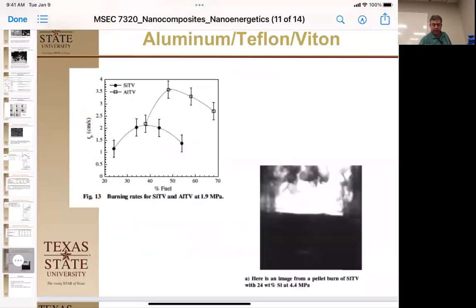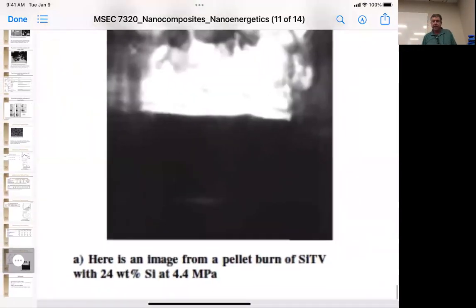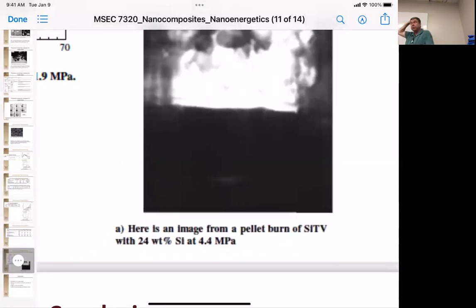Okay. And so what that kind of looks like as they burn, they actually put these pellets on it. They put a high-speed camera on it, and the dark is what they're actually measuring. You're going to measure from where it starts, and then they're measuring how far it goes down over time. And then that right there is all the volatiles that are coming off when they do this. So this is an optical burn. And notice this particular one is the 24%, which is the fastest one for silicon. And they have it at 4.4 megapascals. Again, they're doing it at an increased pressure to emulate being inside a rocket tube, and that buildup in pressure inside a rocket tube for its propellant qualities.